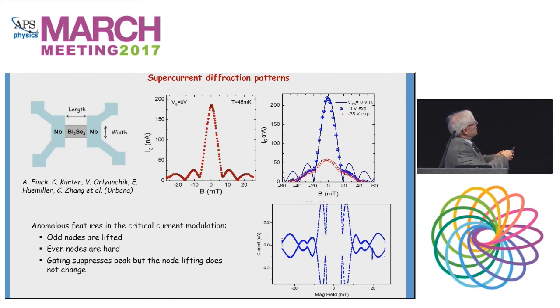Here's one where we did a doping dependence, and notice that this node suppresses with doping. The lobe depresses with doping, but the node is not changed at all. And if you zoom in very close, you can see this has a lifted first node, hard second node, lifted third node, hard fourth node, lifted fifth node. So it does appear to have this even-odd effect.